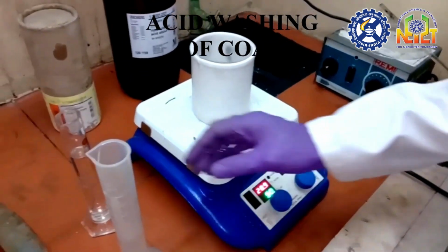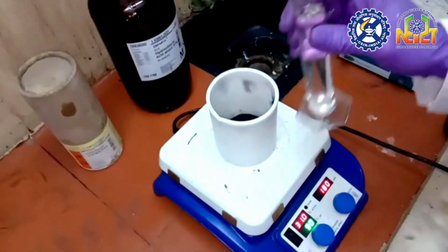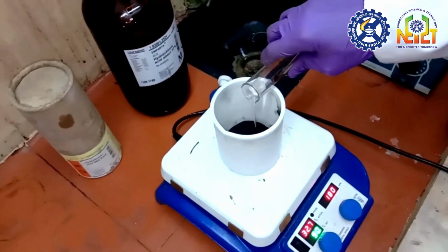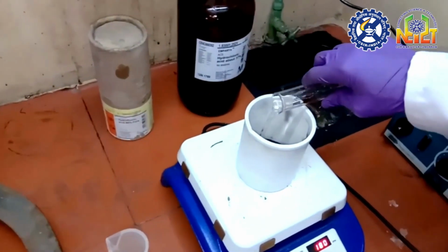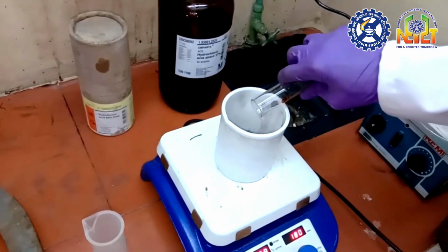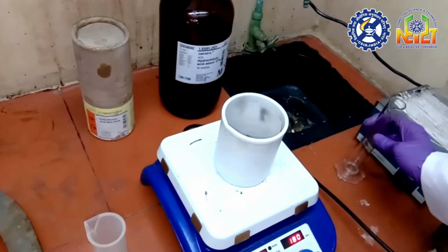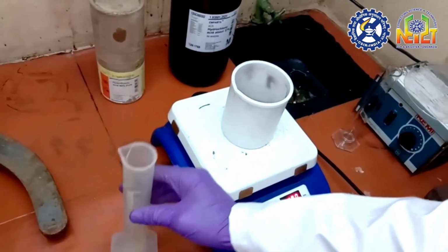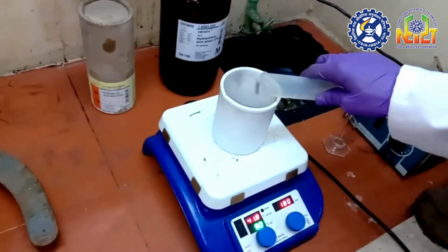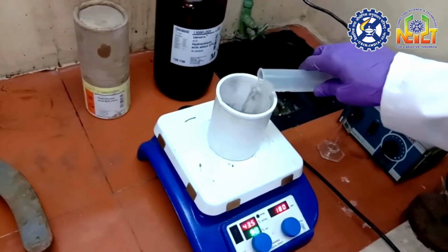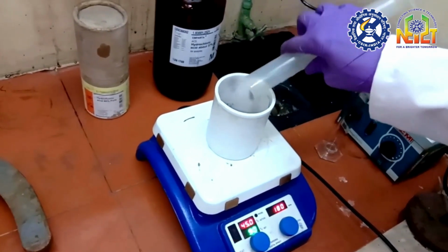The present work basically focuses on the use of low-quality high-sulfur tertiary coals in ultrasonic-assisted production of activated carbons in an efficient process. In order to remove the ash contents of the low-grade NER coal, mixed acids were used in leaching that can be regenerated and recycled into the coal purification system.